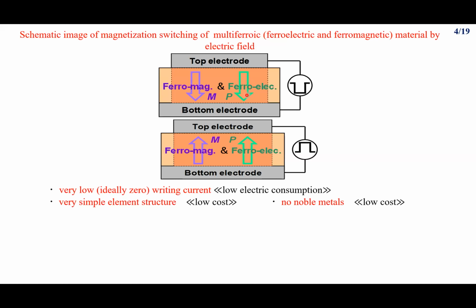So by changing the direction of the ferroelectric, the magnetization will also be switched, which we can achieve by changing the voltage difference. As a result, we could reduce the writing current, which will lead to very little electric consumption. And here the structure is very simple. We are not using any noble material like we use in the case of hard disk drive. So considering all into account, we can use this material to reduce the energy consumption.